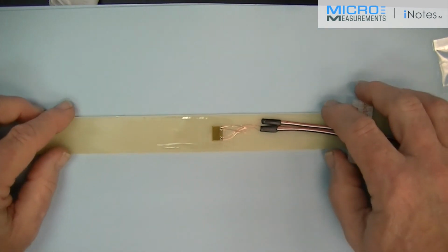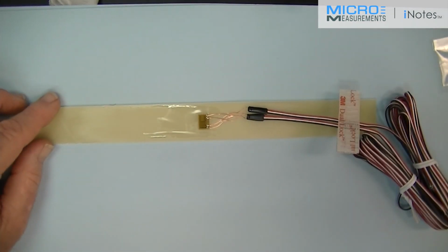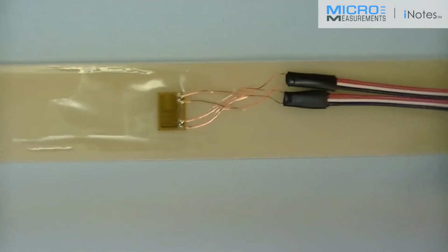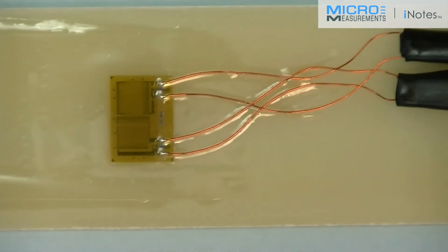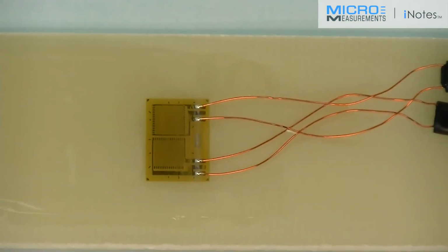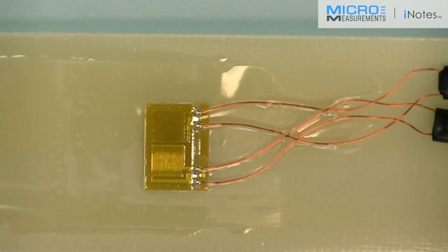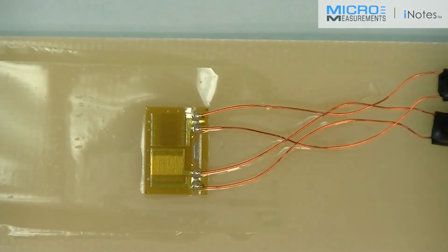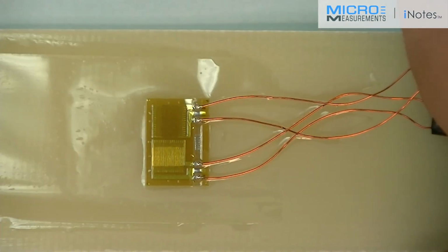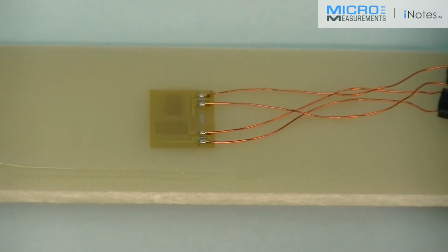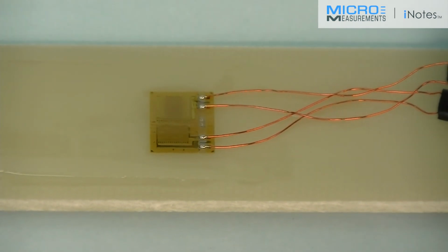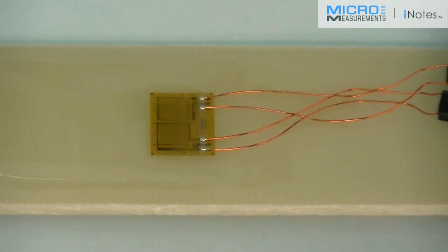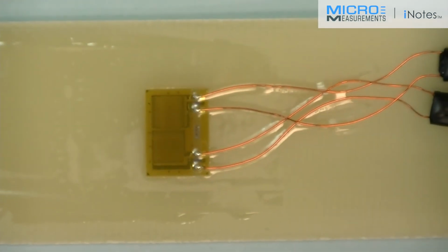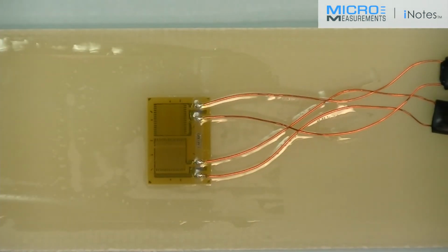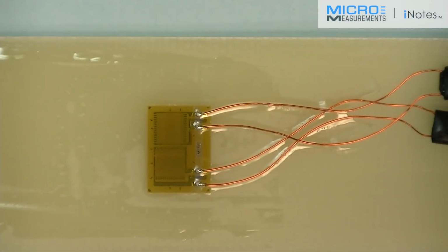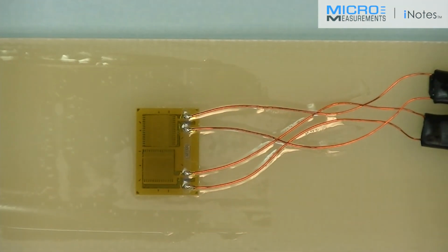Now we want to do a quick visual inspection. We want to make sure we don't have any voids or discontinuous behavior, so we're going to zoom in and look at the gauge. We're looking for a uniform bond line color. We're looking for the little fillet around the edge. We're looking for any debris that might have been trapped underneath the gauge and caused it to have a look of a tent pole or some sort of a discontinuous surface. But it appears, based on my quick visual inspection, that this gauge is fairly well bonded and should make a great C2A installation.